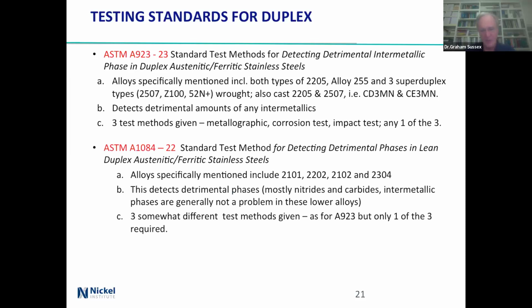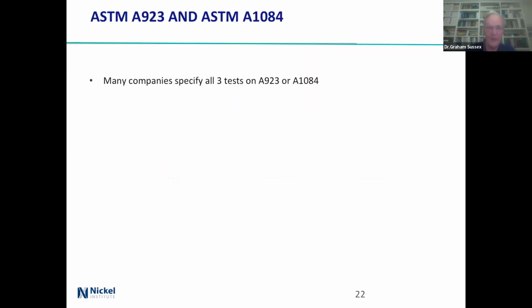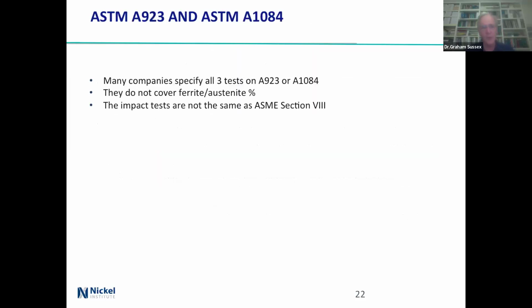1084, well, it specifically mentions those lean and low alloy ones, and it will detect detrimental phases, but the phases we're talking about are nitrides and carbides usually, because for intermetallic phases, there just isn't enough high alloy in there to actually do that. Slightly different tests, but only one of the 3 is required to make it work. A lot of people do all 3 tests on both. One of the little problems is that it doesn't cover ferrite austenite, and you're supposed to be 50-50.